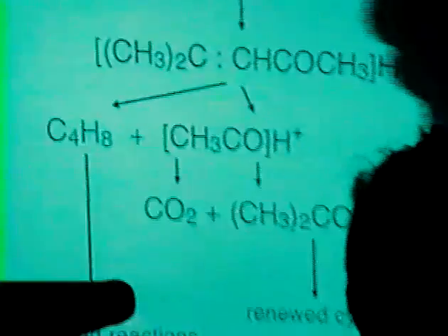When we labeled acetone either in the ketone group or in this methyl group, or used mixtures of labeled and unlabeled acetone, we always obtained the isotopic composition of isobutene that corresponds with the rupture in this position.